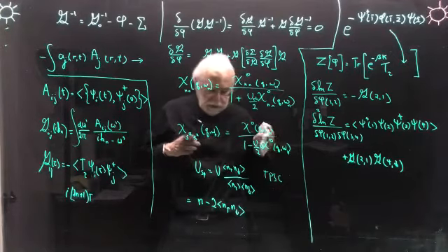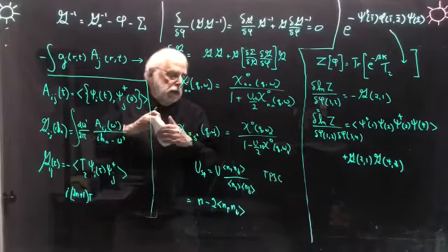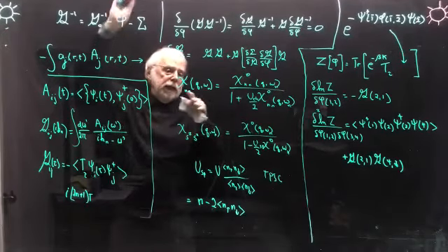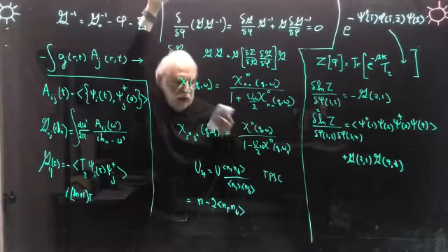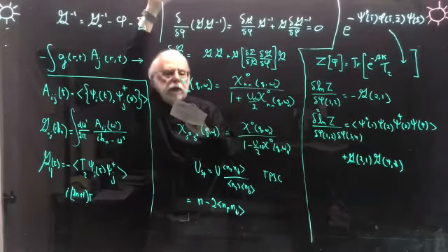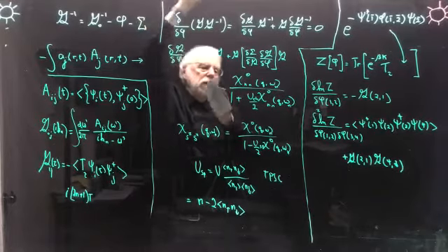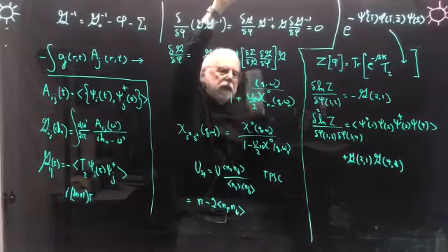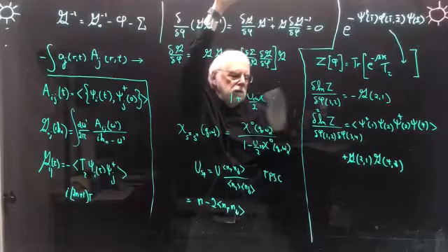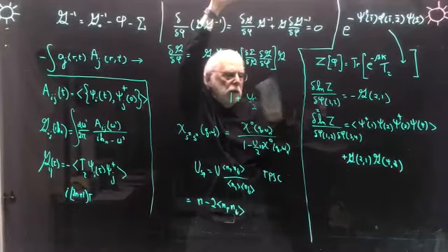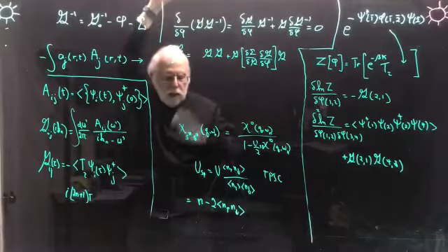And for the self-energy, we do just like we did with the electron gas. We take these susceptibilities, U spin, U charge, and just compute the self-energy. And that can give a pseudo gap, for example, in the case of antiferromagnetic fluctuations. This is what happens in electron doped cuprates, for example. Okay, so now